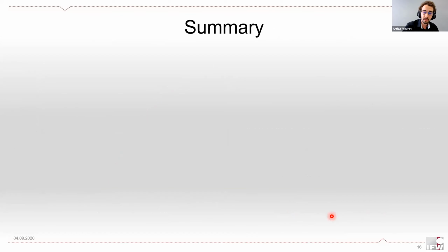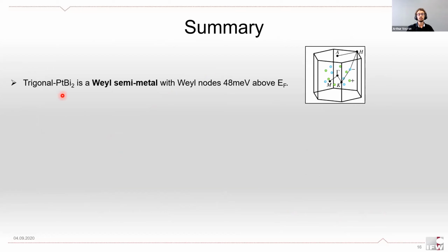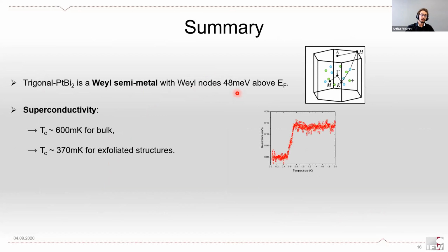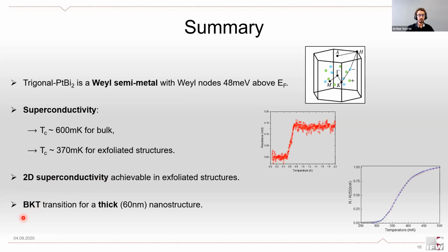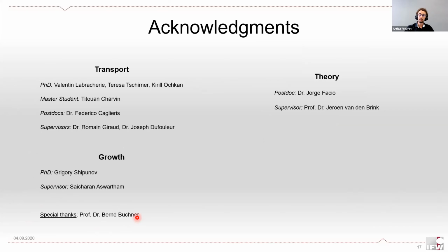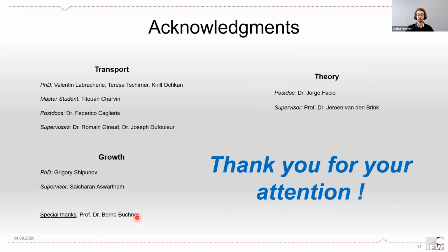So to summarize our results, we have calculated that trigonal platinum bismuth 2 is a Weyl semimetal with Weyl nodes quite close to the Fermi energy. We have found superconductivity in bulk samples as well as in exfoliated nanostructures. We showed that we could reach the two-dimensional superconductivity limit in exfoliated structures, and even that we saw signs of a BKT transition, an inhomogeneous BKT transition, even in quite thick nanostructures. So with this, I come to the end of my talk. I would like to thank all the people that made this study possible, and of course, I would like to thank you for your attention.